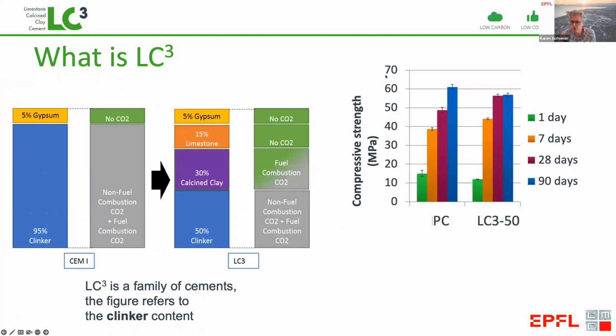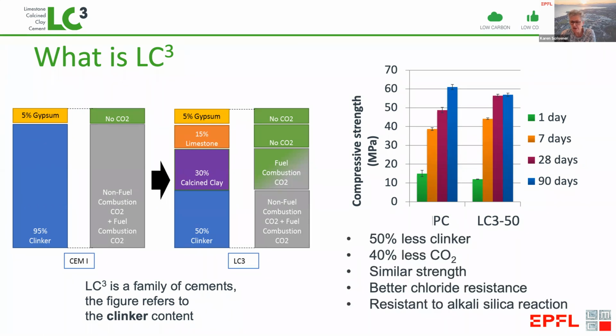But in terms of performance, we can get the same or even better mechanical strength as the reference Portland cement. In only 7 days, with this mixture made in the lab, we can catch up or overtake the strength of the Portland cement, and we can even produce similar strengths at very early ages, like 1 day, if we optimize the grinding. So in summary, we've got 50% less clinker, 40% less CO2, with a similar strength, and some properties like chloride resistance, resistance to alkali silica reaction are much improved.